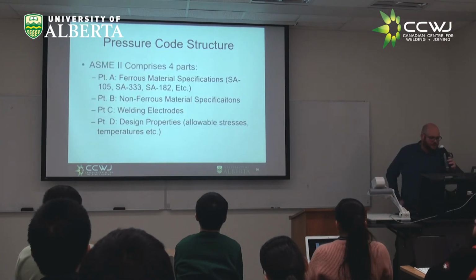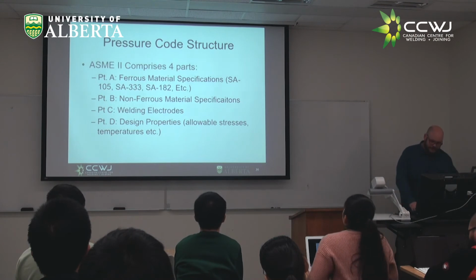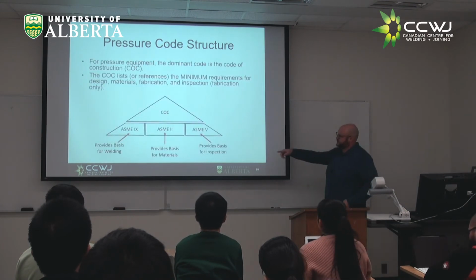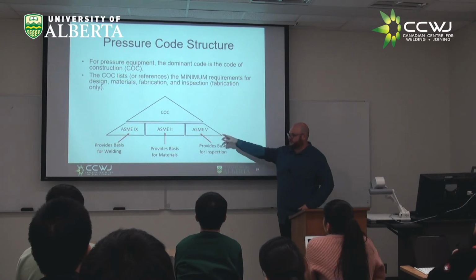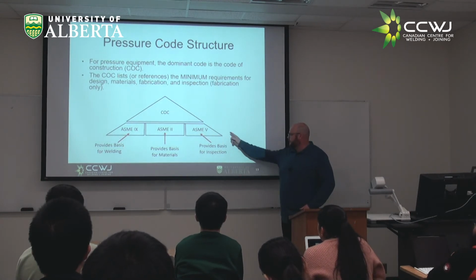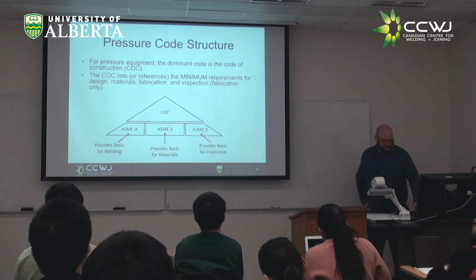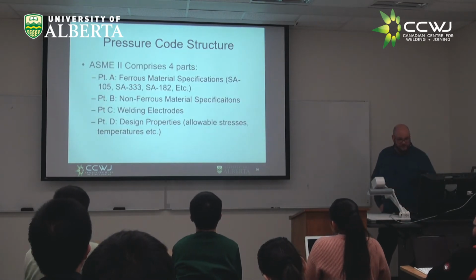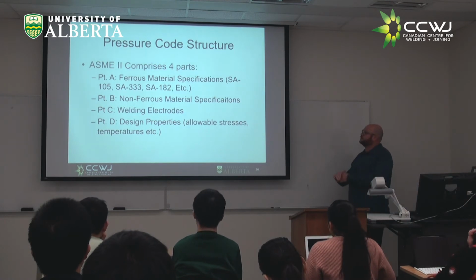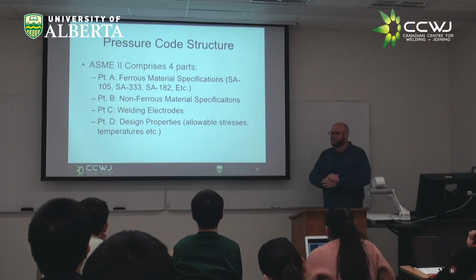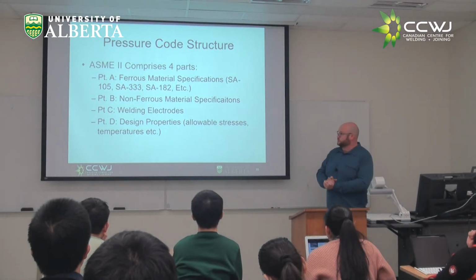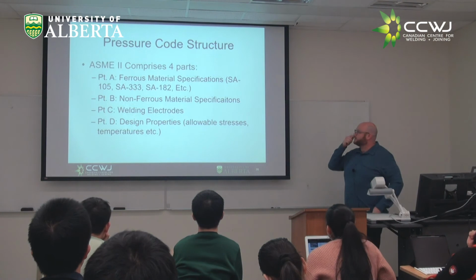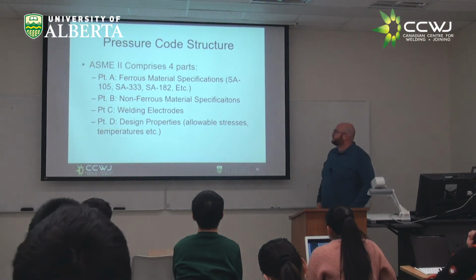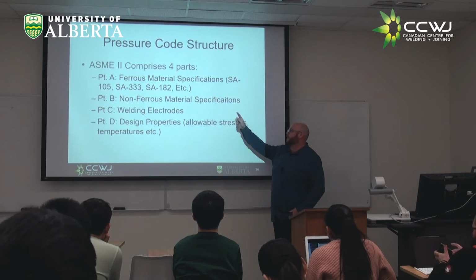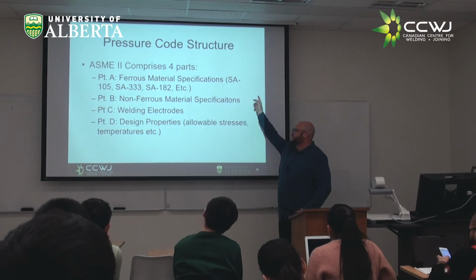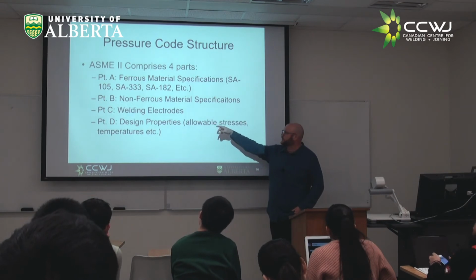So the one thing that I wanted to point out, just to explain, as we were saying, ASME 9 would provide the basis for welding most of the time, ASME 2 for materials, ASME 5 the basis for inspection. So I just wanted to bring up a few things about ASME 2, just because it tends to get glossed over. I'm actually surprised that Aaron brought it up, because most people ignore this and they don't realize what a treasure trove it is. So there's 4 parts to ASME 2. Part A is for ferrous materials, so this covers like SA105, SA333, so the SA is simply A105, so it's your carbon steel piping.